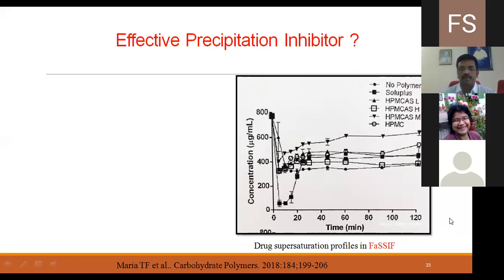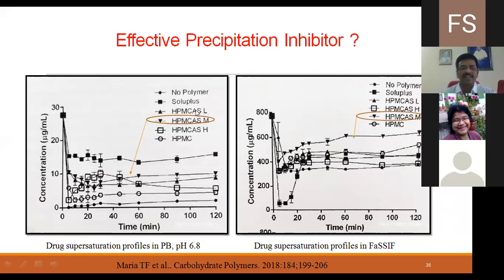If you keep both together, now which is the best PPI? That can be decided. If you observe this, the second best is HPMCAS-M, and in this, the best is HPMCAS-M. Though Soluplus has shown the highest solubility in phosphate buffer, we have to mimic the in vivo conditions. So biorelevant medium was selected and the test was conducted. When it was tested, Soluplus no longer remained in the first place, but HPMCAS-M remained in the top place.